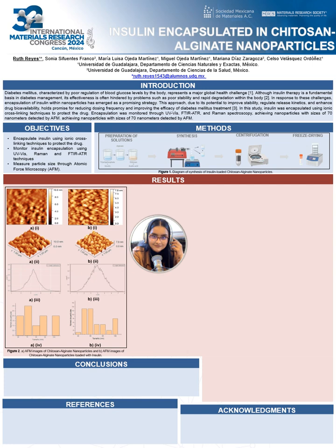Column B shows chitosan and alginate reduced by half but loaded with insulin. As we can see, we are obtaining sizes ranging from 50 to 70 nanometers. Additionally, the sample in column A was deposited by dripping, while the sample in column B was deposited by spin coating, which may contribute to better particle distribution and analysis.